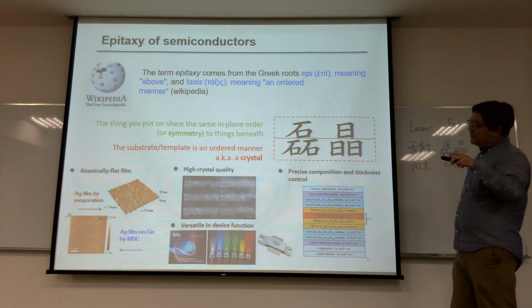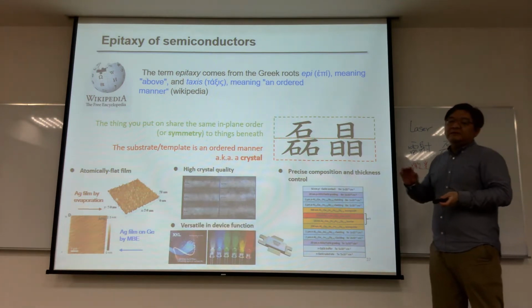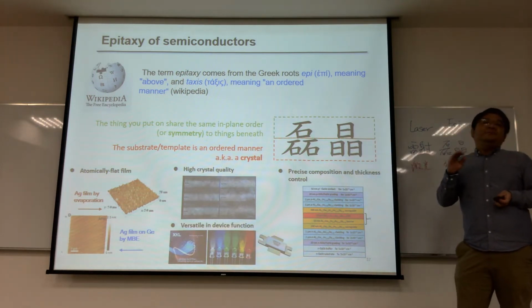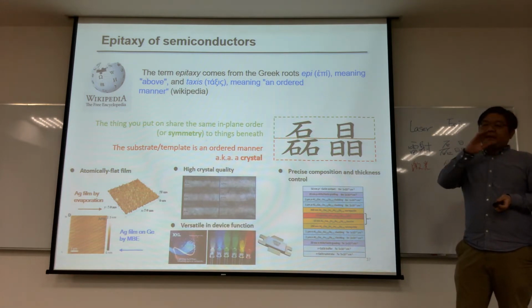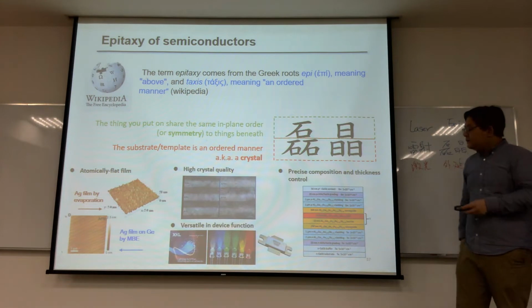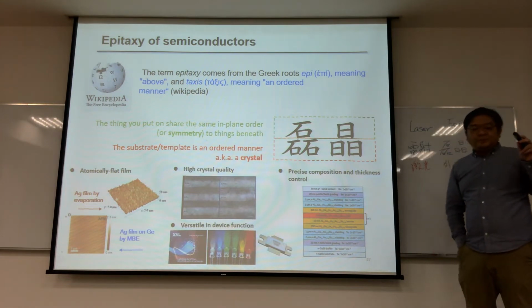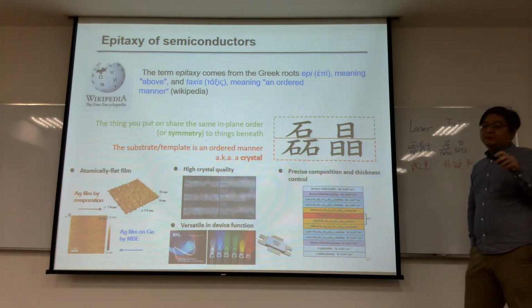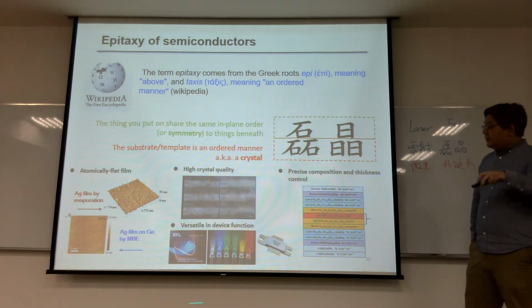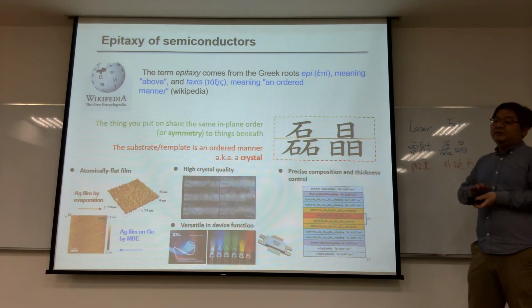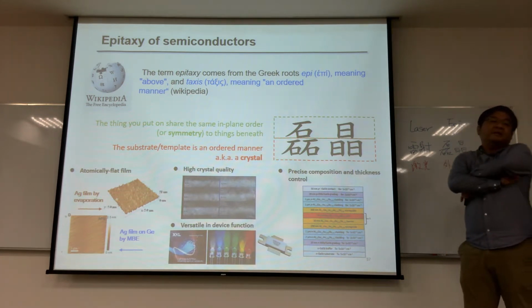And finally, because epitaxy is a very careful process, you do it layer 1, layer 2, layer 3. So if your process is well controlled with your flow and time, you will get your composition layer by layer by layer by layer. So you can have a very complicated structure.